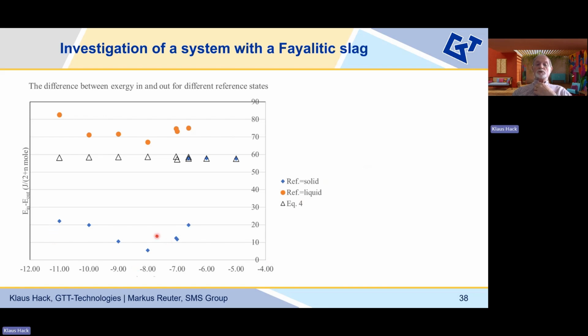And you see here in blue, reference state solid, in orange, reference state liquid, and in the triangles, you see the values calculated from the global formula. Now here, obviously, there is an overall underestimation because we have to choose a reference state if we want to apply that equation with the activities. Whereas when it comes to oxygen partial pressures in the range of stoichiometric solids at the high temperature, there is now agreement between reference state solid and the actual H minus H0, S minus S0 calculation.